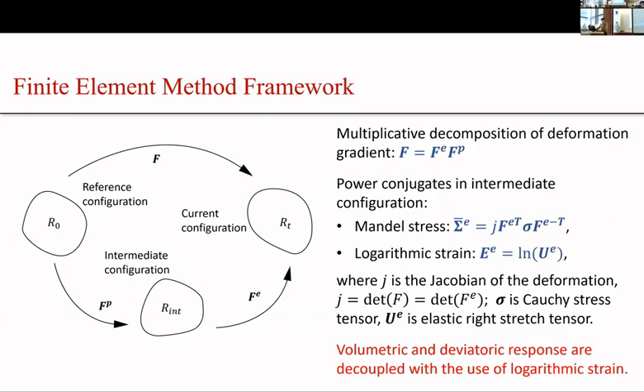The last part of our research, which is the part I'm most proud of, is the development of a finite element method framework that describes the behavior of tungsten carbide under shock loading. In this part, the deformation gradient tensor has been decomposed into a plastic part and an elastic part. That way, between the reference and the current configuration, we have an intermediate configuration. The power conjugates we used in this framework are the Mandel stress and the logarithmic strain, expressed in those two expressions. They are quantities in the intermediate configuration.